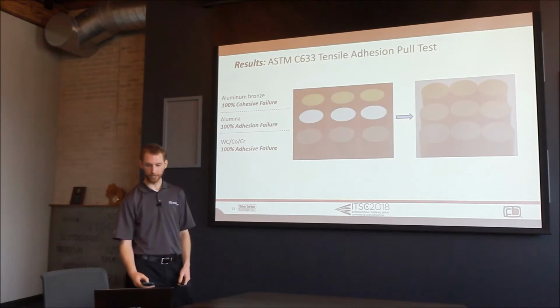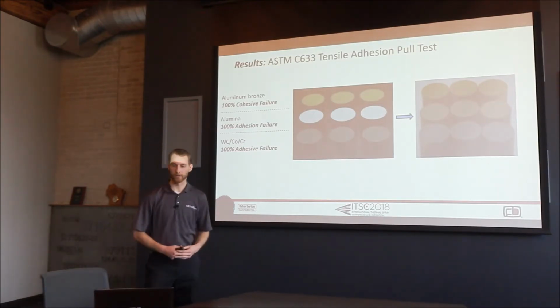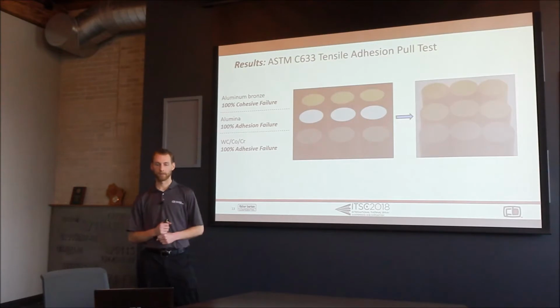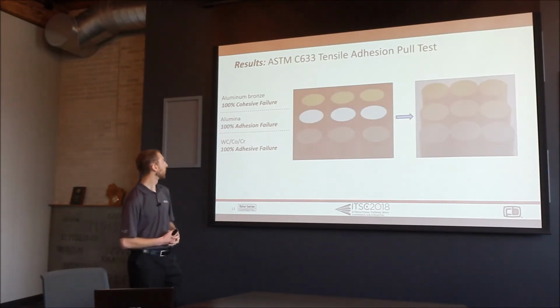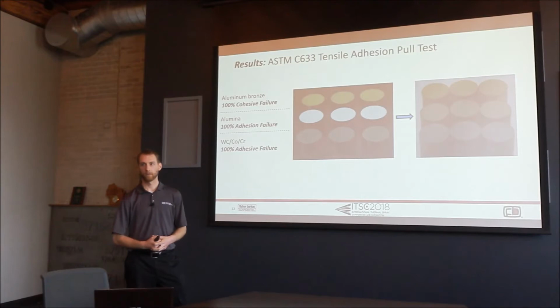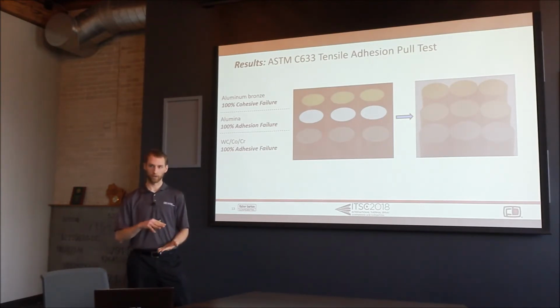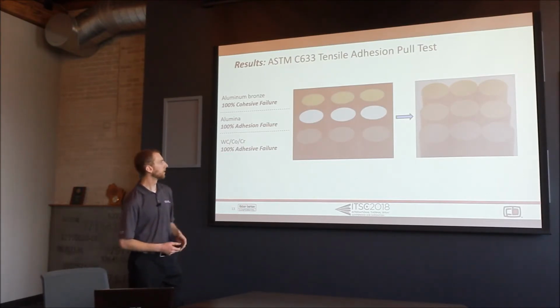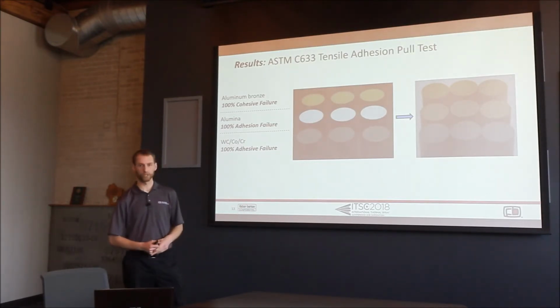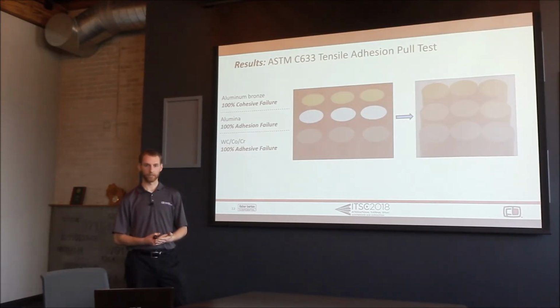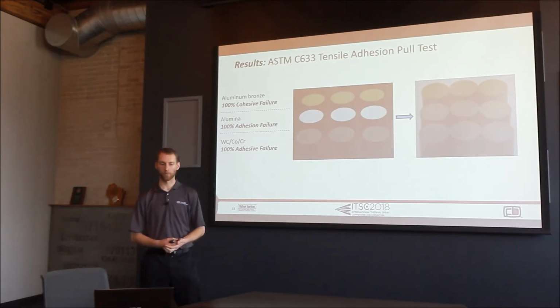With C633, these are the standard tensile bars. So, 3 examples here. With the aluminum bronze, we had a cohesive failure. That coating failed completely within the coating and not at the interface. In comparison, with the alumina coating in the middle, we had complete adhesion failure. That coating did delaminate at the interface. And then with the tungsten carbide cobalt chrome 8610-4, that was 100% adhesive failure. So that one outlasted the adhesive strength itself.